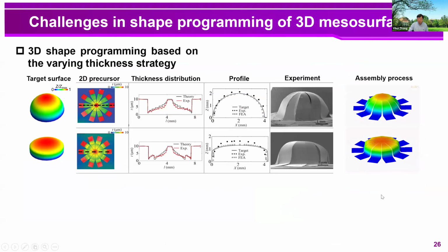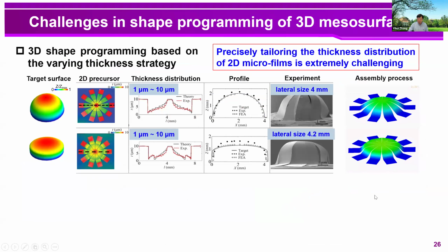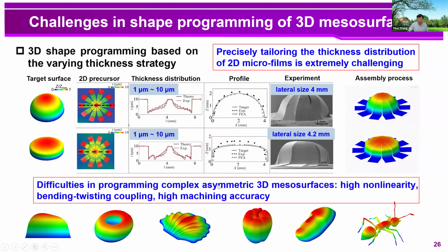But for the thickness variation, the fabrication is extremely challenging because it's very challenging to achieve precise tailoring of the thickness variation for 2D films, especially for electronic materials. And actually, according to our previous studies, by using the grayscale photolithography, the thickness resolution we can achieve is just 1 micron. And by using this kind of technique, the smallest structure we can achieve is a hemisphere with a diameter of 4 millimeters. But at this scale, you can also see a large distortion of the assembled structure from our design target. So here the challenges include the high nonlinearity, the bending twisting coupling, and the high machining accuracy. So it remains very challenging to program highly complex 3D surfaces at the micro scale.